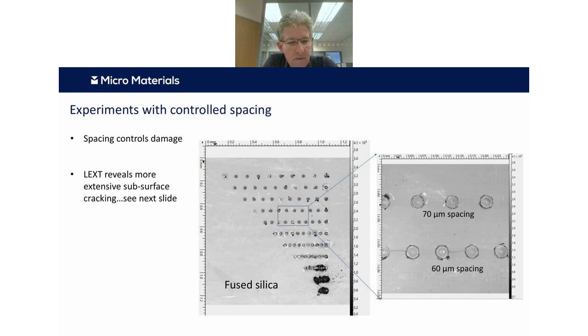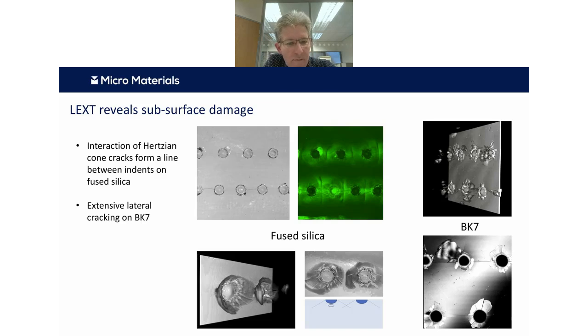And we're starting to get, by 60 microns apart, a few of these cracks joining up. So we used, this is the contrast image. We're also at MPL, they were looking at the green light images, and that reveals a little bit more about what's going on.